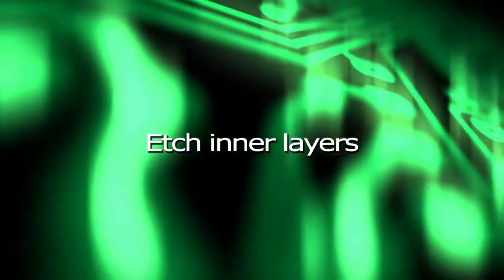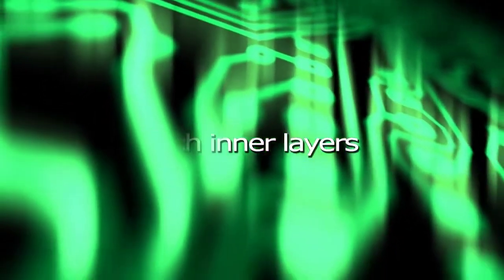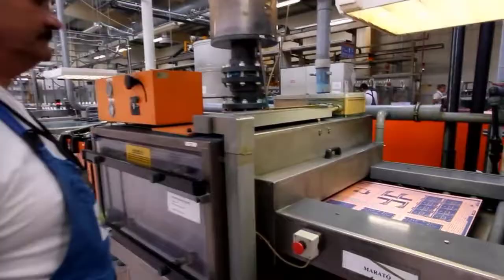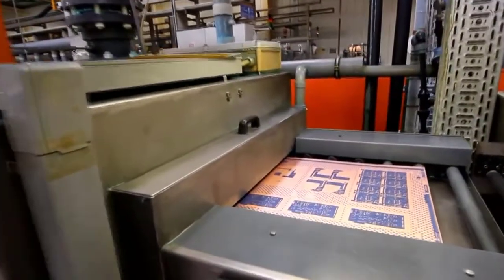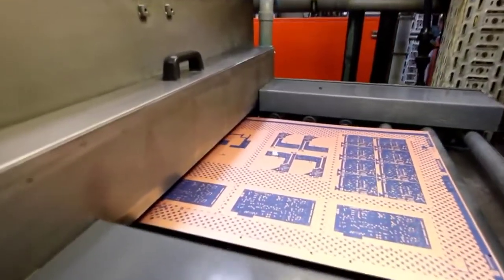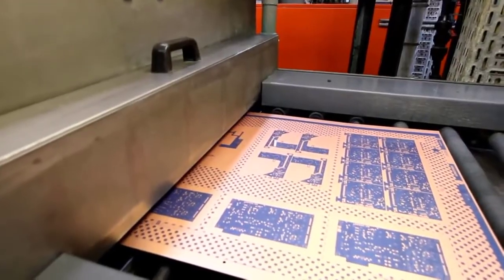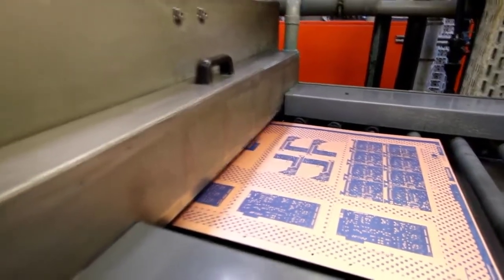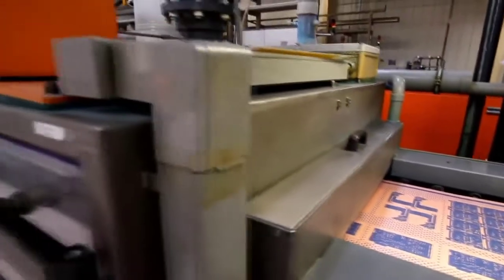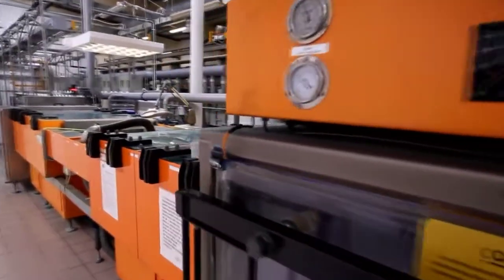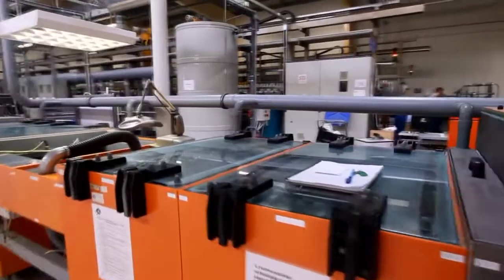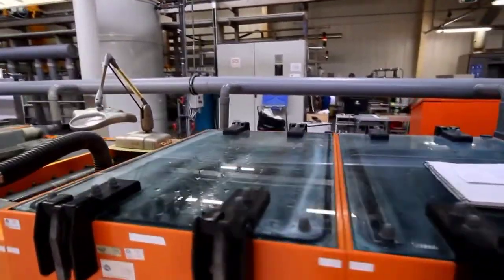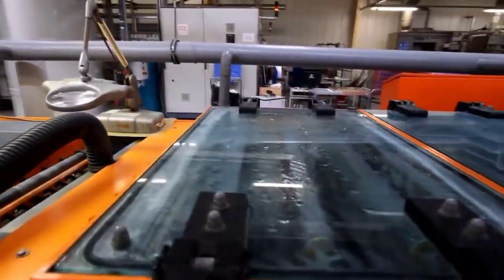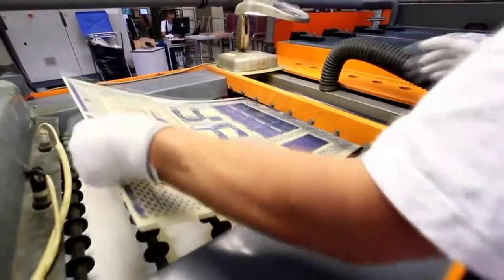Etch inner layers. We remove the unwanted copper using a powerful alkaline solution to dissolve or etch away the exposed copper. The process is carefully controlled to ensure that the finished conductor widths are exactly as designed. But designers should be aware that thicker copper foils need wider spaces between the tracks. The operator checks carefully that all the unwanted copper has been etched away.